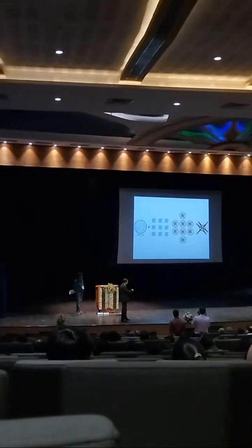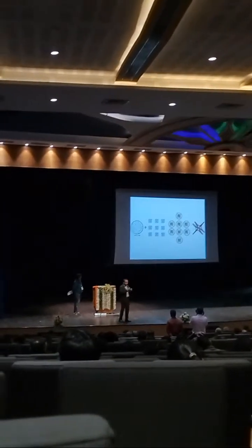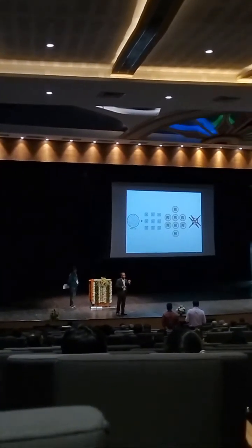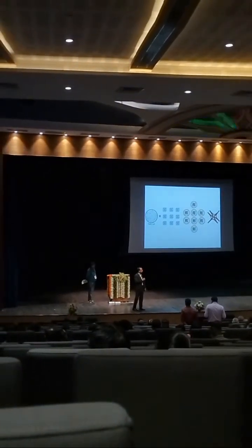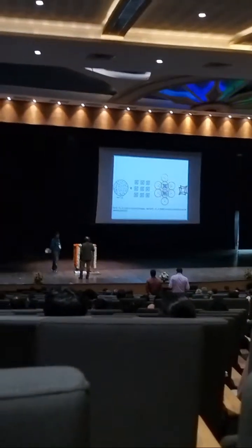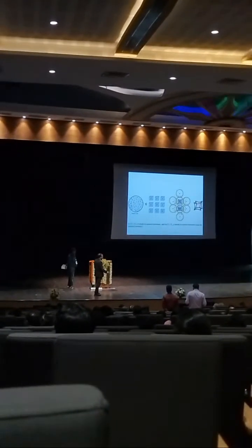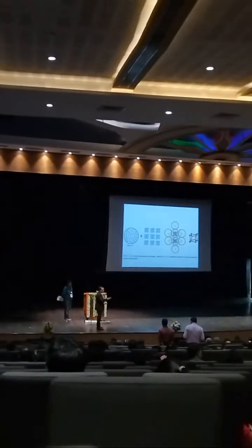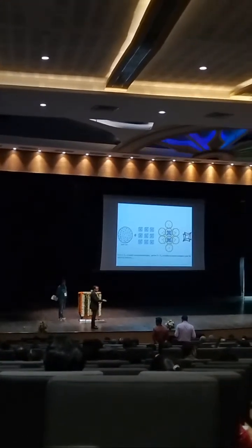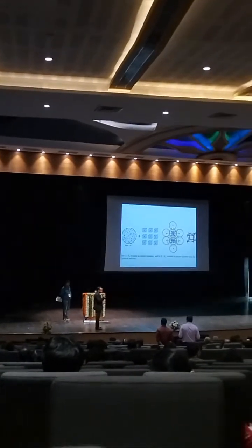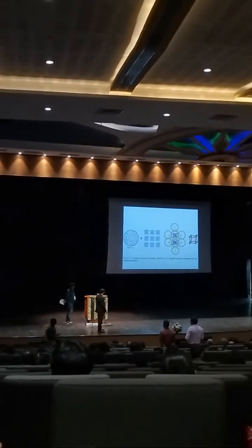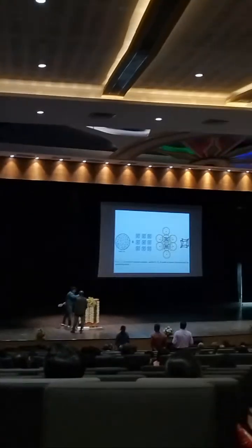A few shapes we make are without surfactant, using very small molecules like ascorbic acid, and those molecules give a huge Raman signal. Generally we try to make structures that don't use much surfactant. CTAB is a good surfactant for stabilization, but a bad surfactant for SERS because it makes a plastic-like coating outside. Thank you, I got your point.